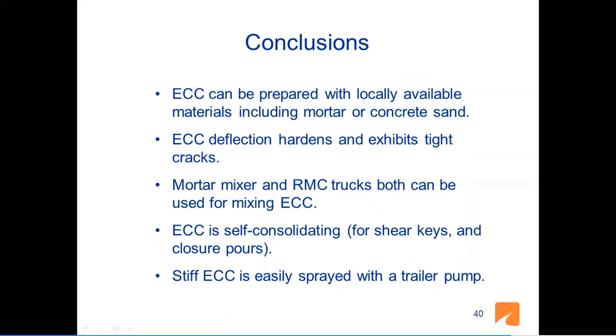So in conclusion, we have been able to do ECC, engineering cementitious composite, with locally available materials, including mortar or concrete sand. And concrete sand is what they prefer at the plants. And ECC deflection hardens and exhibits tight cracks. And mortar mixer and ready-mix concrete trucks both can be used for mixing ECC. That depends on the amount of ECC you need. Small ones in mortar mixer, large quantities in the truck mixers.